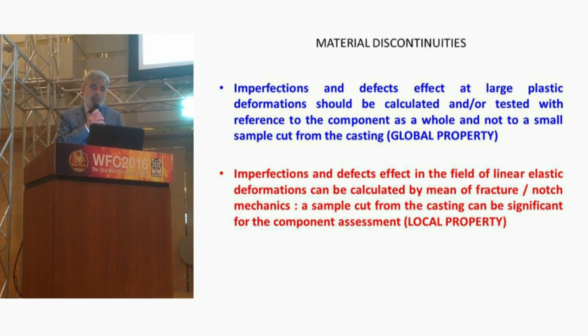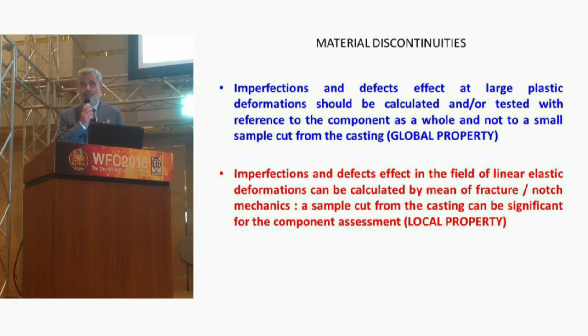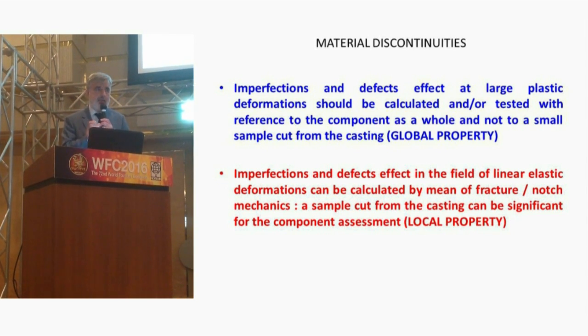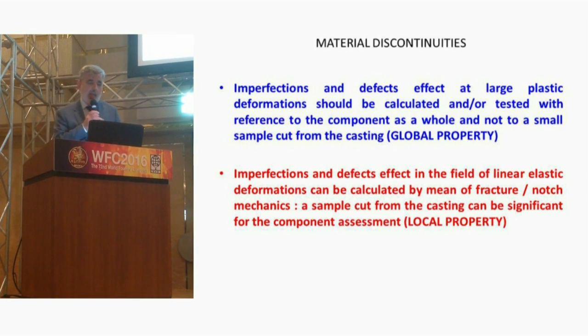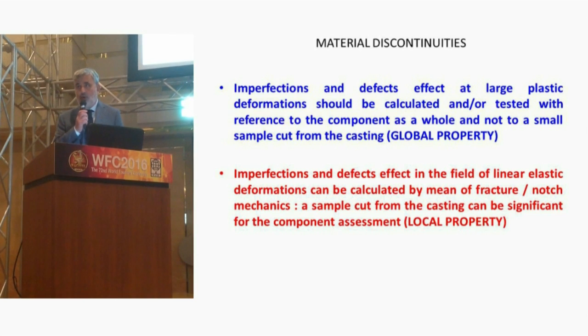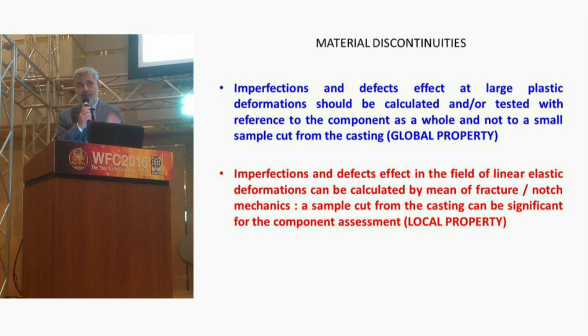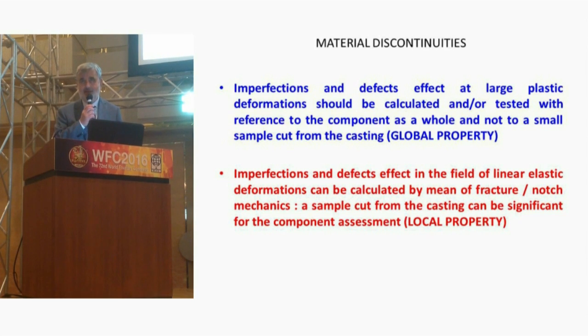So I suggest that when we are considering large deformation, as in the tensile test, we should not use test probes with some defects, as there are sometimes in the castings, as a material quality test. This is a test of material quality and defect at the same time. While when we are talking about fatigue, fatigue is a local property. If I have a failure on this side, independent of the other sides, this will make the crack start, and so the fatigue of the casting will be affected.